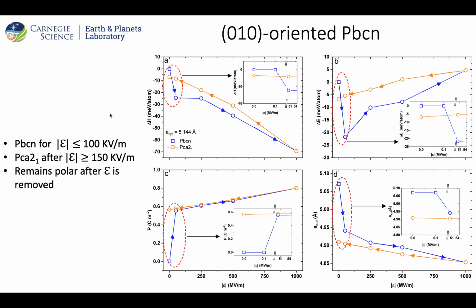And so as we increase the magnitude of the electric field, this ferroelectric phase stabilizes even more. And then as we decrease it, it stays at the PCA2/1 phase, all the way to whenever the electric field is turned off.